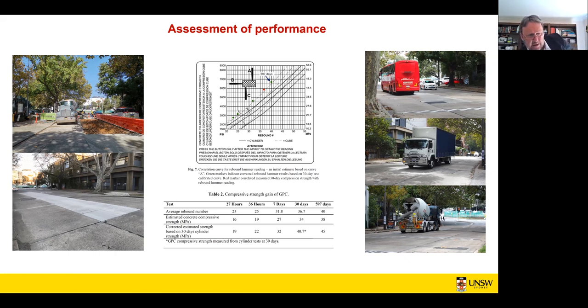So this end part here is really the end of the truck. So about 13 metres we're monitoring here. And you can see the rebound hammer tests. So after 36 hours, we've got about 22 megapascals of strength. And at 597 days, 600 days, we've got about 45. So it's still performing, it's still hard. There's no indications of wear along wheel lines, in either pavement, both are performing quite to expectations.